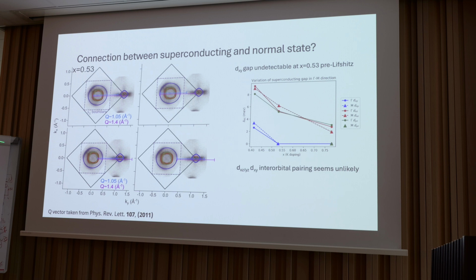one of the arguments made in the fully potassium doped paper was that the reason the XY band is zero around gamma is that it's close to the S plus minus boundary. But we see that around 53%, where the gap is zero, it's not that significantly close to the S plus minus boundary, and it's not too different from 41%.